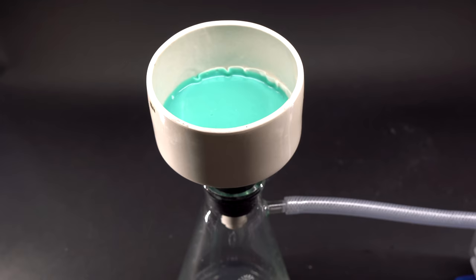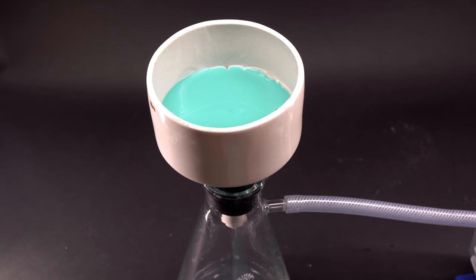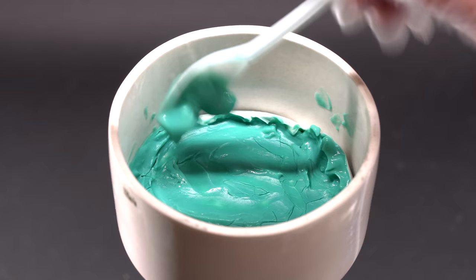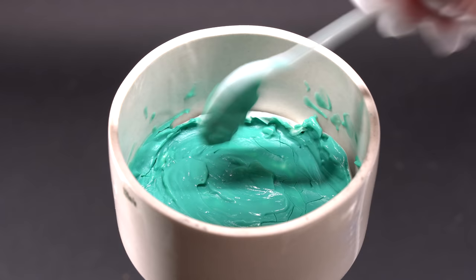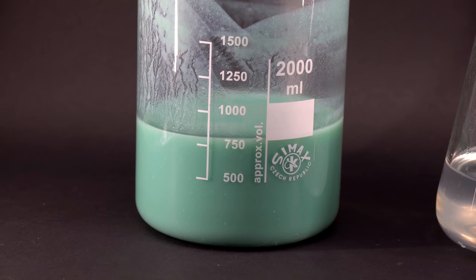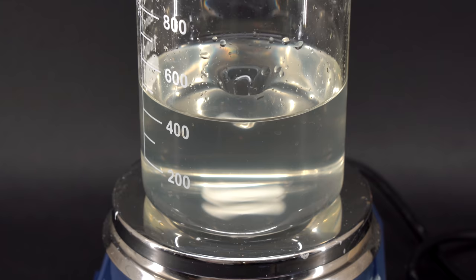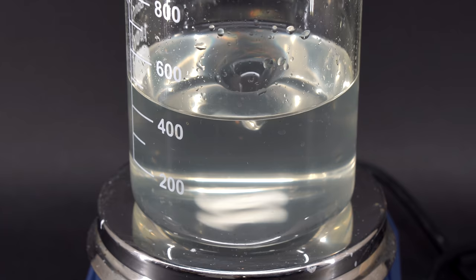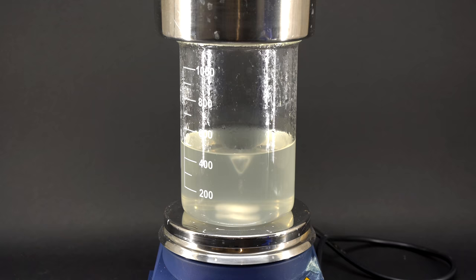As a result, a nickel and cobalt hydroxide sediment of such light green color sinks to the bottom. If needed, later, nickel and cobalt can be separated from each other. But now my main focus of interest is extracting lithium from the solution rather than side metal compounds. The only problem with this greenish sediment was that it was too fine and when filtered with a suction filter, it would turn into something like clay, which made the whole process last forever. Eventually, in order not to burn my vacuum pump, I filtered only half of the solution. I think it's enough for extracting lithium. In the end, I got a transparent liquid containing a mix of sodium sulfate, ammonium sulfate, and lithium sulfate, which I need to separate again and extract lithium compounds from this solution.